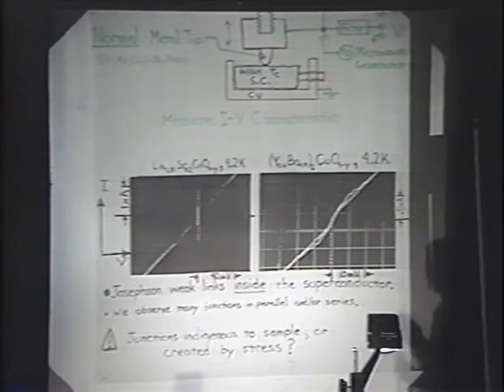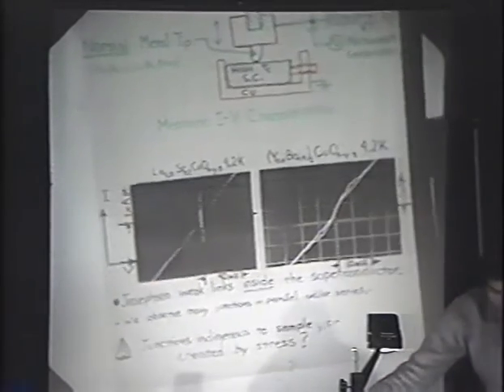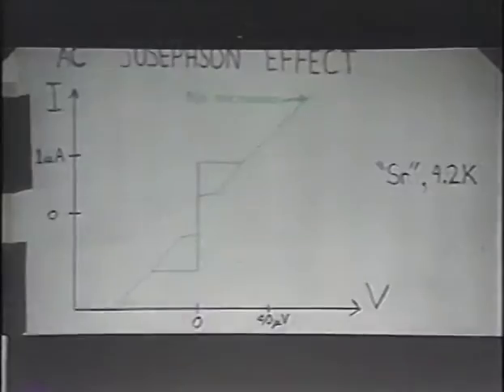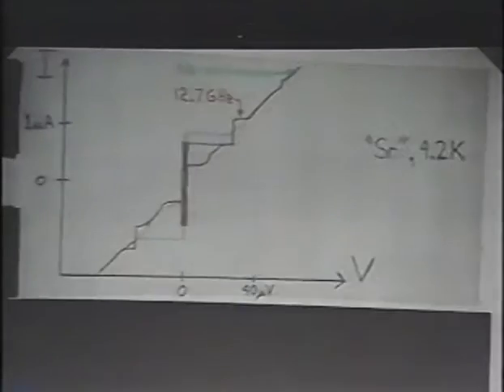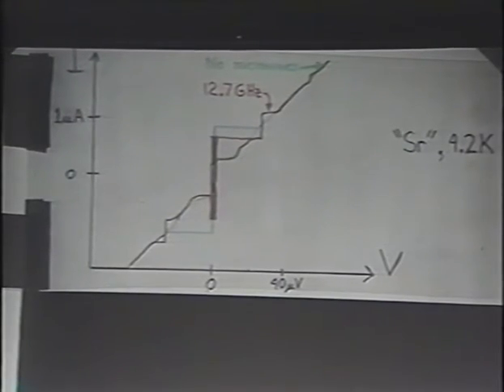Let me note that we don't know whether the junctions are indigenous to the sample or if they're created by stress when we push the tip against the high TC superconductor. Anyway, no matter where these things come from, we can use them to find out some information about this superconductor. So what we do is look for the Josephson effect. Without microwaves, we get an IV structure like this. We put on microwaves, we see steps, quite characteristic of the AC Josephson effect.